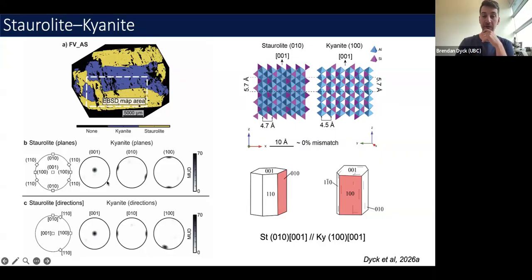So looking at staurolite here, we can see, for example, the pole to the 001 plane of kyanite overlaps with the pole to the 001 of staurolite, as does the pole to the A, so the 100, overlaps with the poles to the 010 of staurolite, right? So we have this very clear orientation relationship.